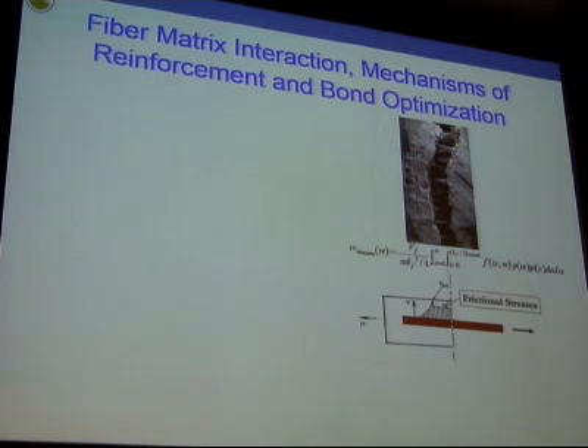So when you start analyzing that one single fiber which is now bridging the crack, a number of models have been developed which tell you how a fiber essentially pulls out of the matrix, because you're trying to maximize its pull-out capacity. And when you're trying to maximize its pull-out capacity, you're also making sure that the fiber doesn't fracture in the process. A number of patents have also been generated in designing these fibers which pull out at the highest resistance, but do not fracture in the process itself.